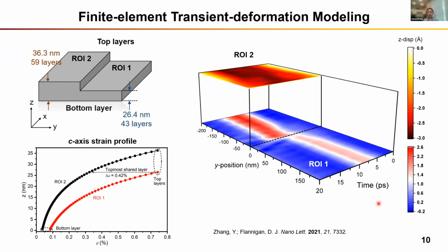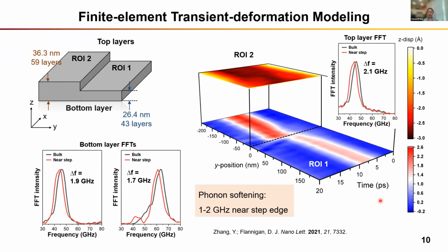So the contour plot on the right represents the z direction displacement as a function of time. I then computed the FFT of the time-dependent z displacement near and far away from the step edge. So the bulk frequencies are shown in the gray, and they're pretty close to the experimentally observed values.